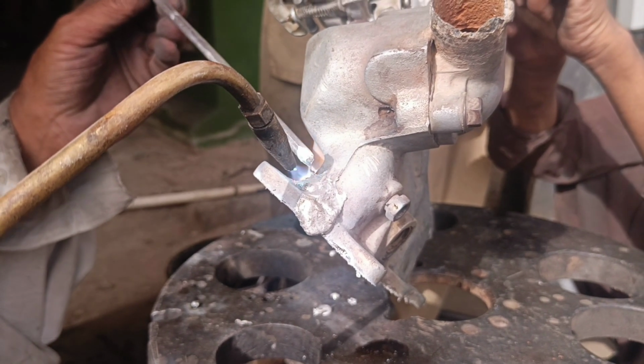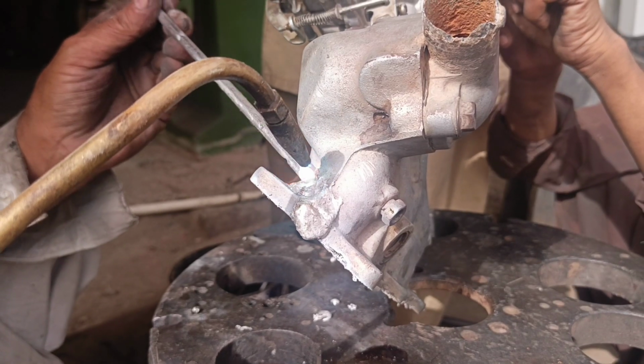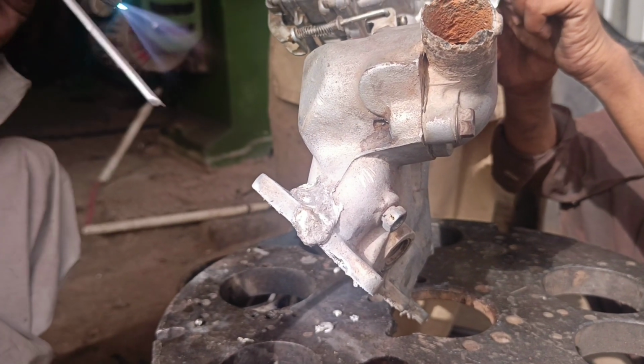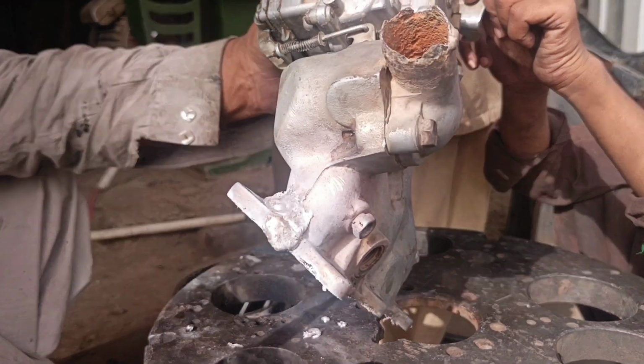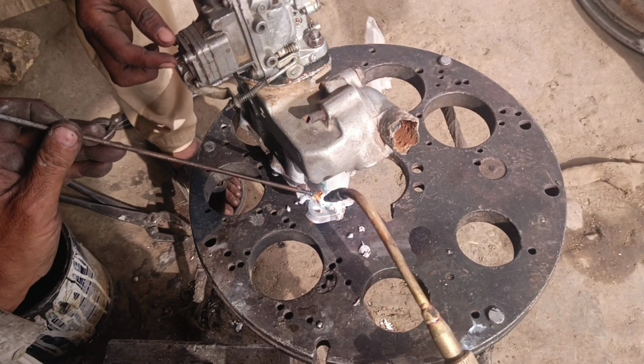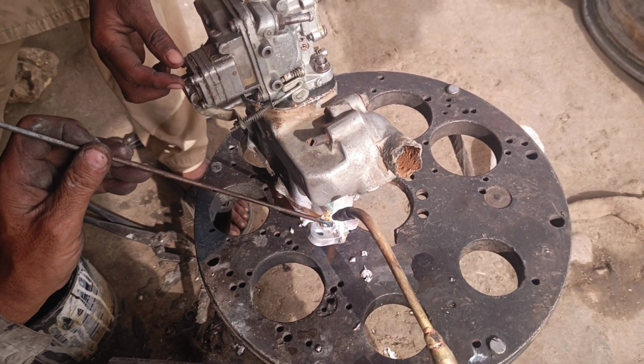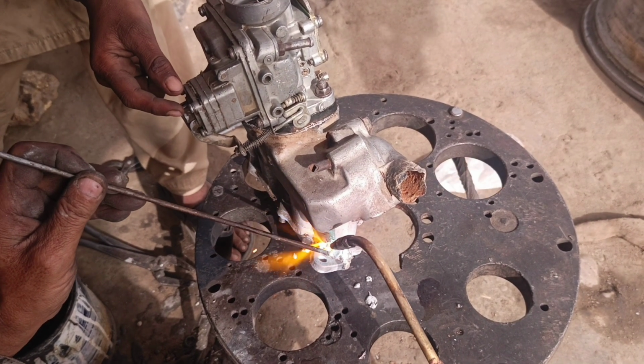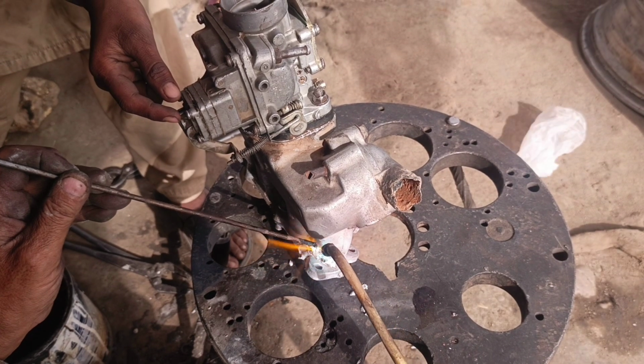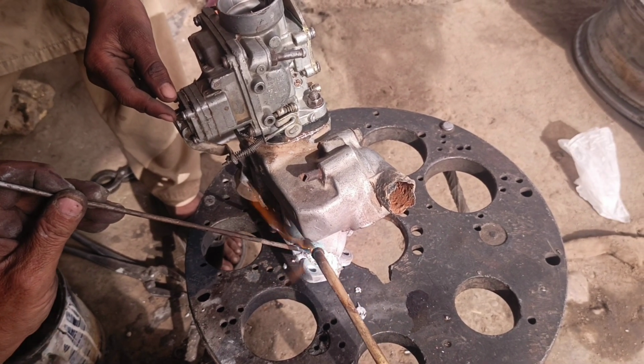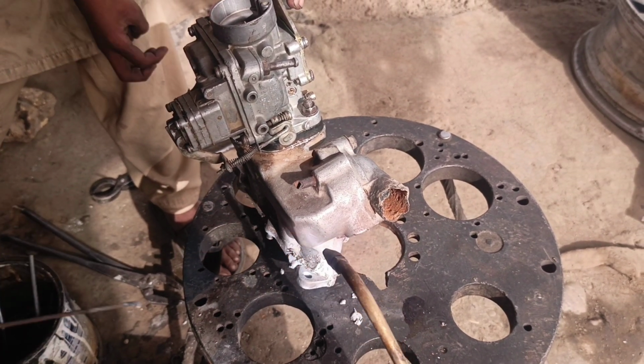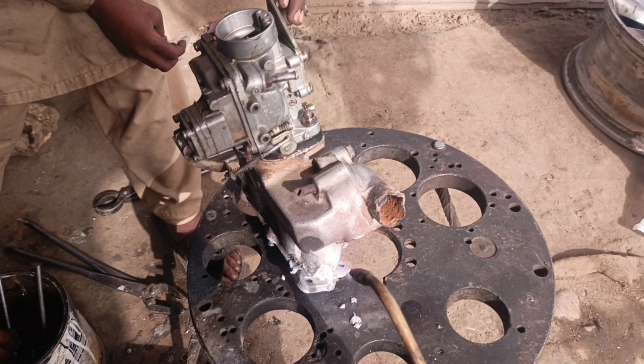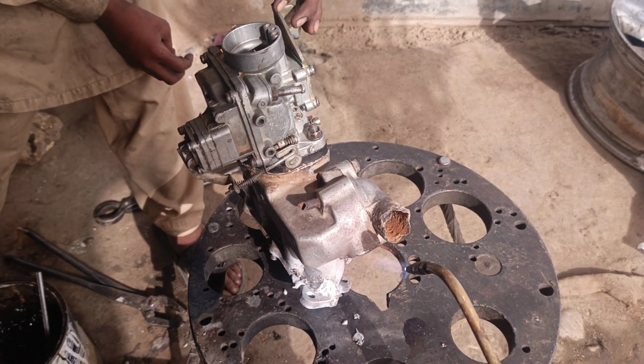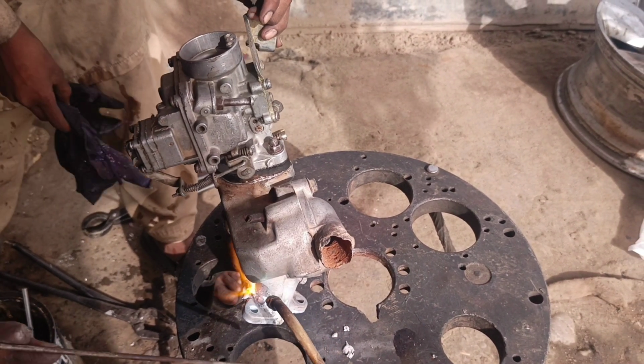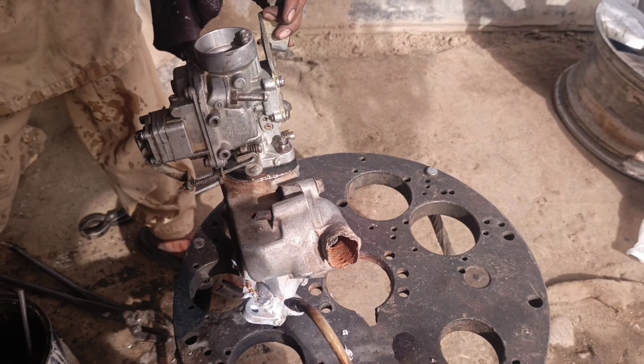filler metal. The oxygen and acetylene cylinders are checked, the torch is adjusted to produce a neutral flame, and the carburetor is slowly preheated to prevent thermal shock and reduce the risk of additional cracks. Once the aluminum reaches the correct temperature, the mechanic begins gas welding by carefully melting the edges of the crack while feeding an aluminum filler rod into the weld pool. The torch is moved steadily to ensure even heat distribution and a strong bond without overheating the casting.